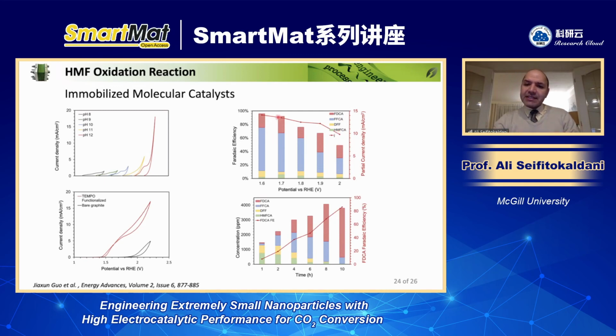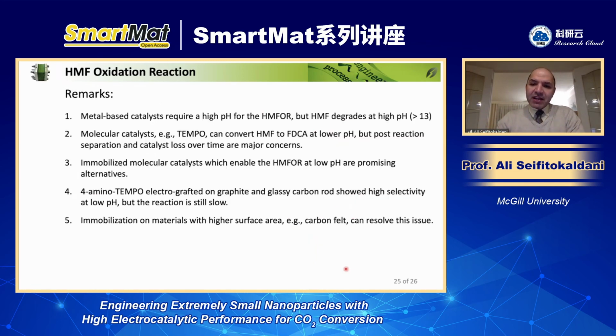So for us in this case, 1.6 volt was the optimum voltage. But as you see, applying that voltage for a short time, like 1 hour, is not good enough because although you are converting the HMF to different products, as we mentioned, HMFCA, DFF, FFCA, and also FDCA, if the target product is FDCA, 1 hour is not enough. You need to work with that system for a longer period. So that's also a challenge coming with this system. But it's quite selective, and also it doesn't really need alkaline environment.